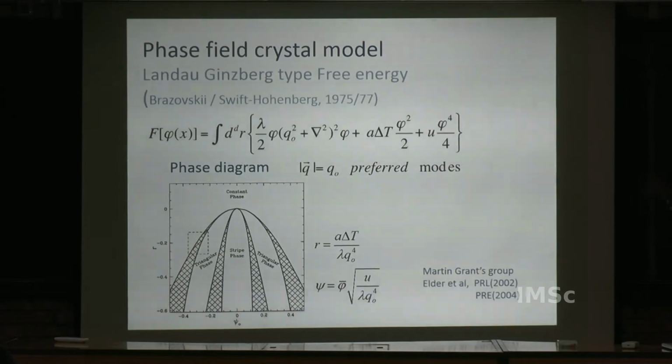Now you can see that you are just preferring a particular magnitude, you are not preferring any particular vector. So one can say that you are preferring an isotropic thing. The Q0 is isotropic. You have not put in any particular vector which will help you form a certain type of lattice. But it was just an accident that they found that when you simulate in 2 dimensions, it has low energy states as a hexagonal crystal, which is known to be the minimum energy state.